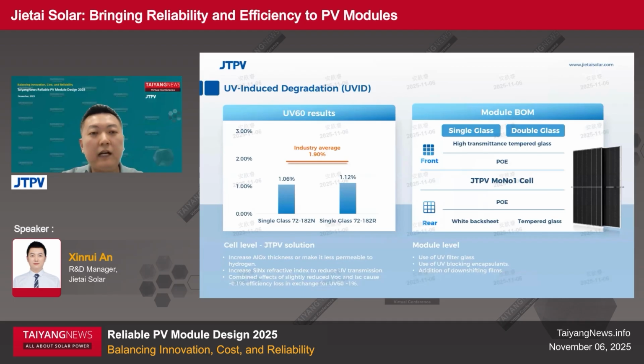In JTPV, we developed a specific front passivation scheme for customers who require very low UVID. We've made several changes to the front passivation stack. Not only does the surface become less dependent on hydrogen passivation, which is very sensitive to UV, but the amount of total UV absorption by the cell is also greatly reduced. And to make the surface less reliant on hydrogen, we could either increase the thickness of aluminum oxide or make this layer less permeable to hydrogen, which inevitably leads to a lower VOC.